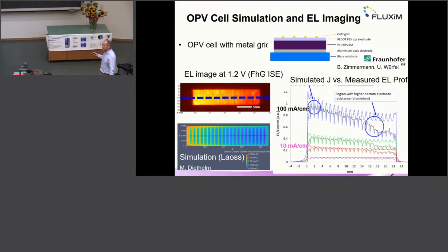There was PEDOT:PSS as a conductive electrode material with limited conductivity, and the exact value of this conductivity needed to be adjusted in the model in order to reproduce the measurement. That's how you can fit the measurement in the simulation: adjust some of the unknown or estimated values of conductivities, such as PEDOT:PSS.